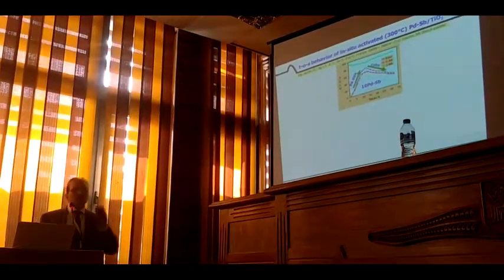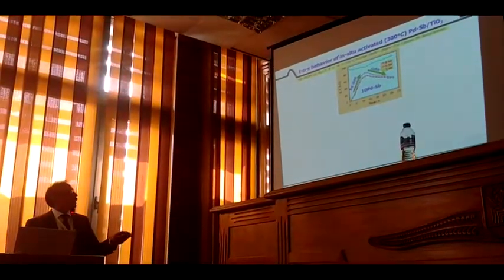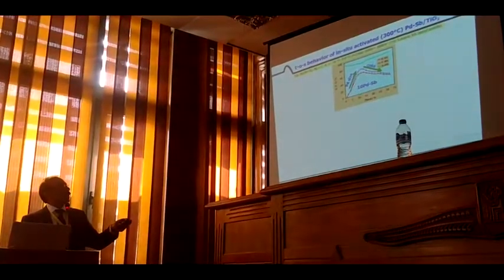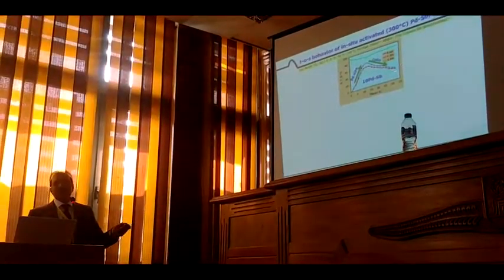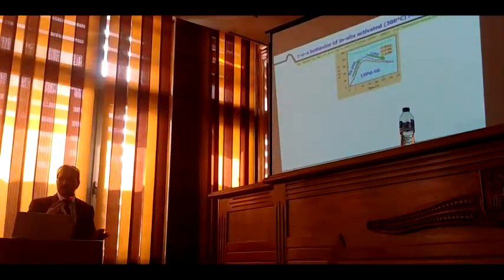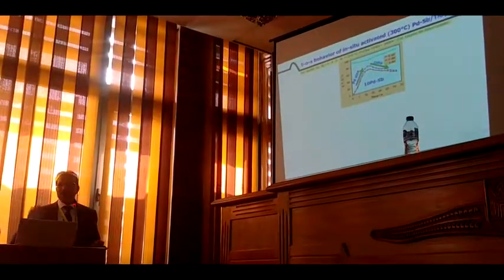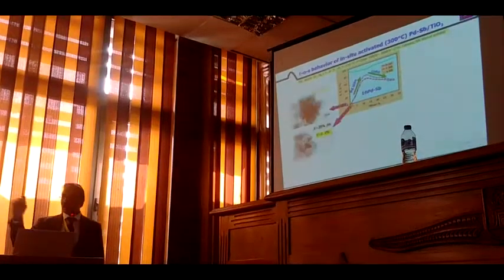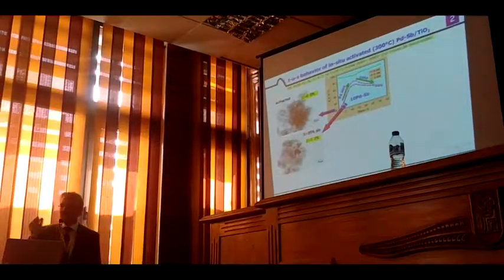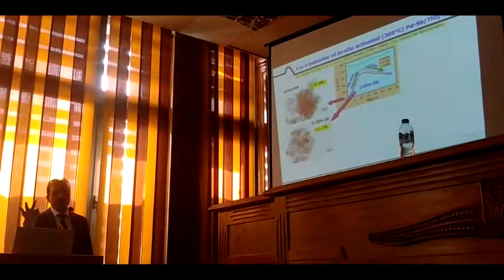So what we have done, we have collected samples at different stages of reaction: the fresh one, the half active one, the maximum active one, the deactivated one, and the regenerated one. And we checked the particle size. We stop the reaction after 5 hours and immediately analyze by TEM. We stop the reaction at 10 hours, immediately analyzed. So now I request your kind attention to watch carefully, because here we are going to see three changes: change in palladium particle size, change in the conversion, change in the coke deposition.